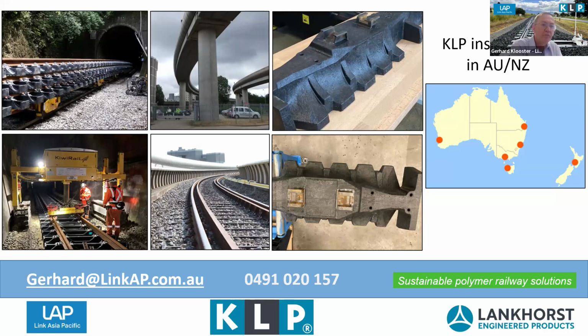No, we have not done that. What we have done is, part of the initial development testing was fatigue testing and cycle testing and exposure to 2 million cycles and measuring the stiffness before and afterwards and the degradation after 2 million basically fatigue cycles. I have the reports here. If you want to, I could send them through for you to have a look at. There's extensive test reports. I must say the product was developed in Europe. It was developed against ISO 12856, which basically caters for standard sleepers, for bearers, and for transoms. We have extensive test results, derailment, impact tests, etc. A variety of test results available.